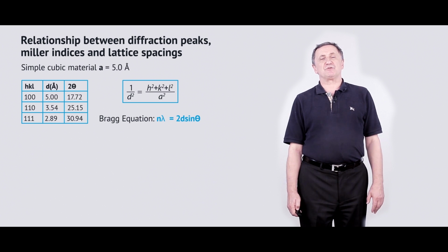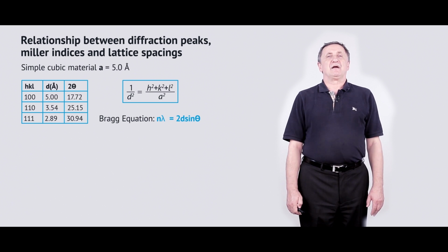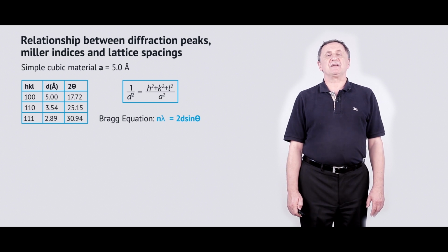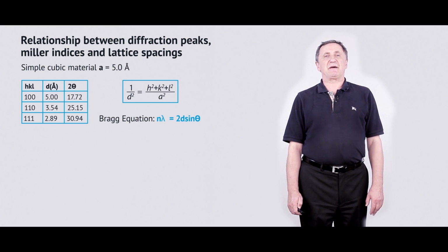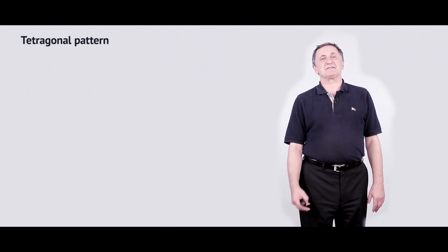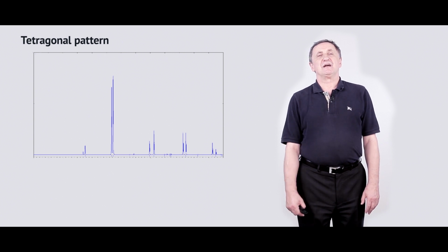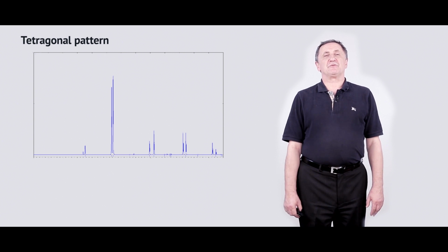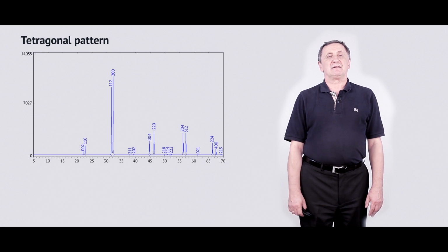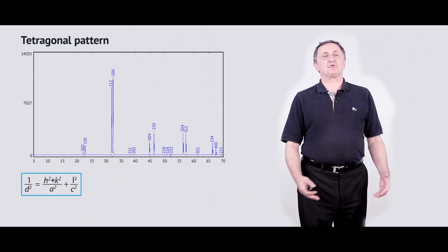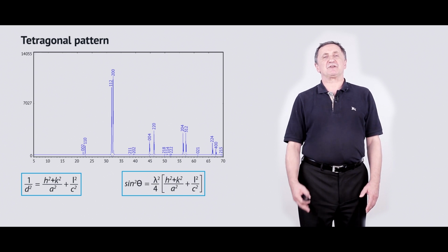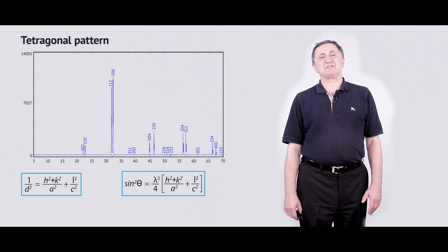So that's the general approach. It's not bad to know how to find the relation between the diffraction peaks, Miller indices, and lattice spacing. Then you go to the database, and these cards show you what kind of parameters, d-spacings or even diffraction angles correspond to this type of phase, and then you have to match your measured parameters with the parameters in the database.